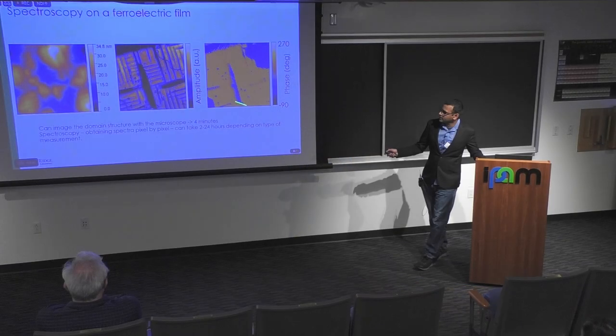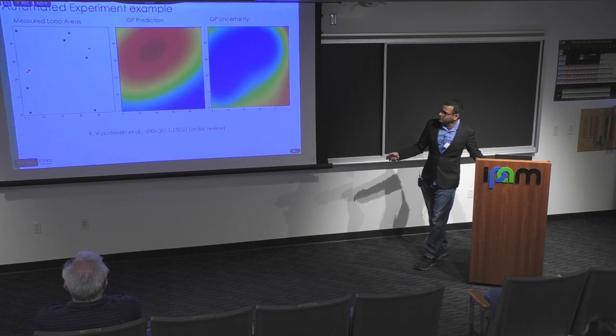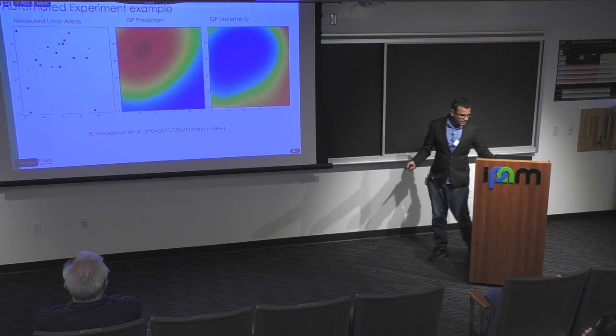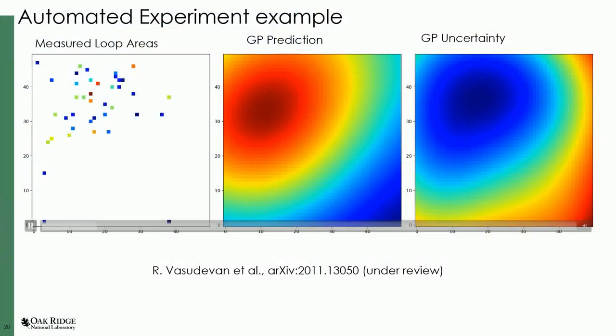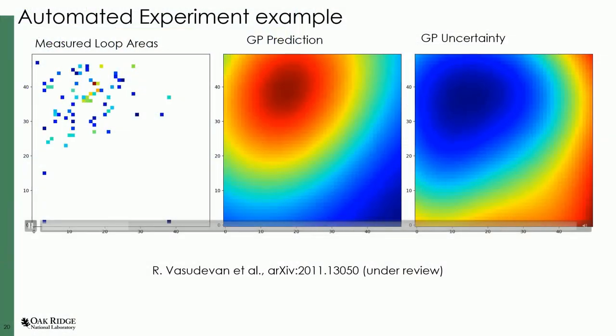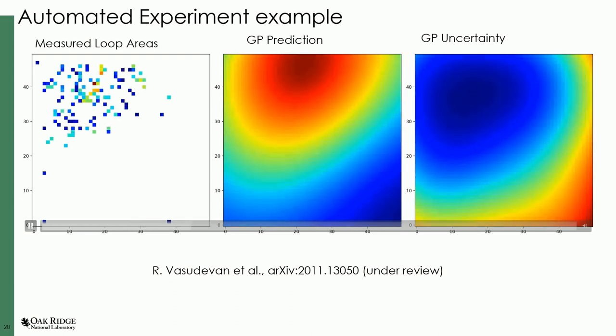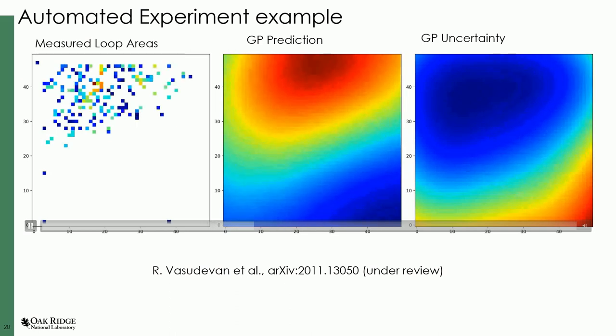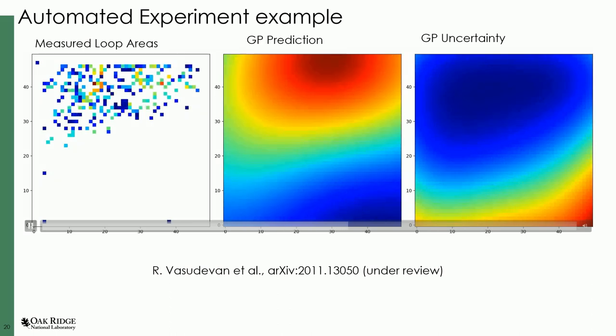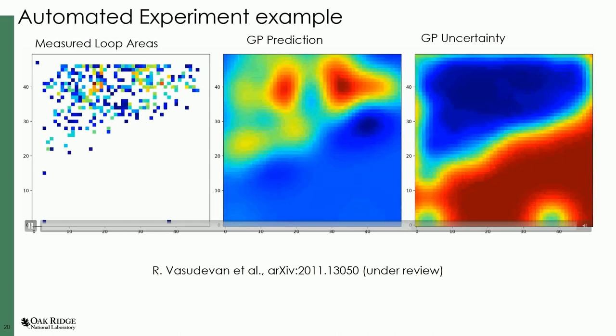Again, this is just an image that we collected of the sample before we started the experiment, and this is showing what the experiment actually looks like. On the left, you see some random pixels that have been sampled. In the middle, you see a prediction from the Gaussian process regression about our particular target property. It's very broad and large, and you don't really see much for now. But once you get to a particular number of spectra sampled, you'll see some localization where the kernel length scale in the GP prediction is well optimized, and you see this transition.